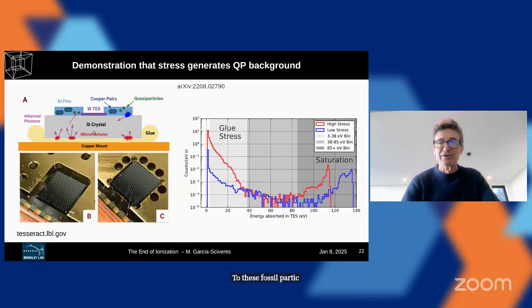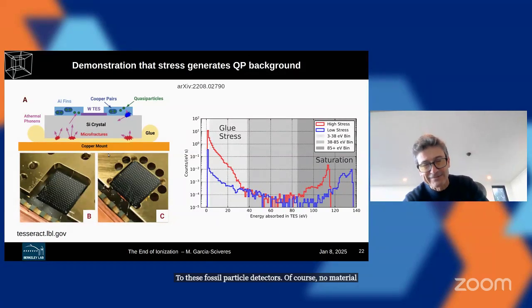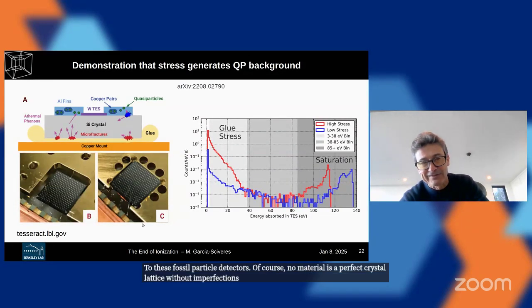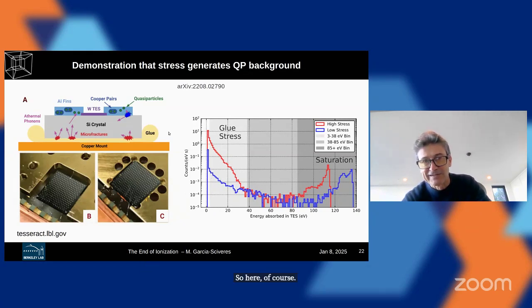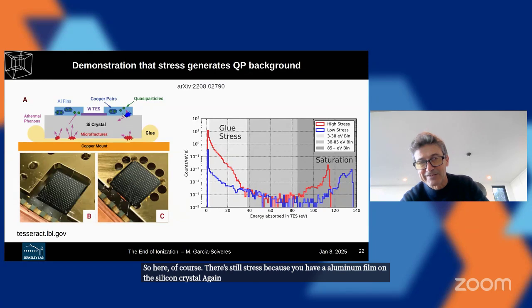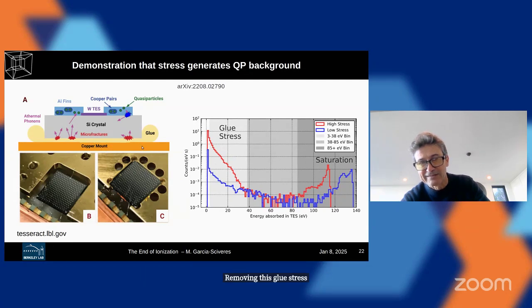Of course, no material is a perfect crystal lattice without imperfections, and so you can see that this is very hard to get rid of. So here, of course, there's still stress because you have an aluminum film on a silicon crystal. Again, there's a CTE mismatch there. There's going to be stress here. That's what this remaining blue is. Removing this glue stress doesn't get rid of anything going on at the sensor, and this is it.